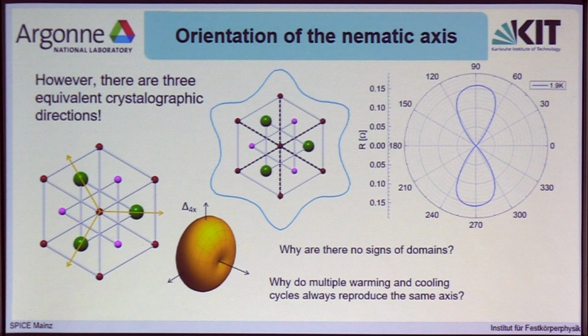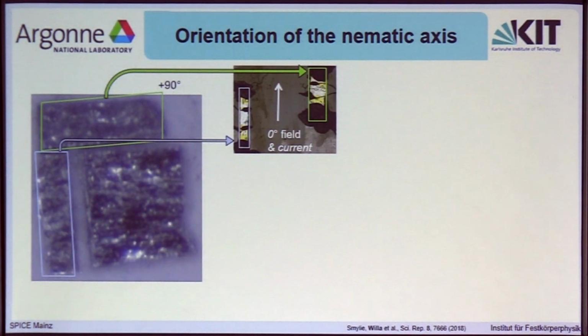The second thing: even though we don't see any domains, what people also report in all kinds of experiments is that if we warm and cool the sample multiple times through the superconducting transition, not only don't we see domains, but also the same orientation of this preferred axis is picked each time we cool again. So it doesn't look like it picks it randomly, but like it has a preferred orientation. To investigate this more, let me come back to the experiment I showed you before.